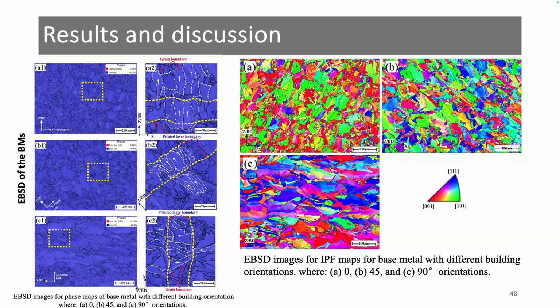Here we show the EBSD of the base metal. This one was at 0 degree, here 45, and here 90 degree. We can see that this dashed yellow line represents the printing layer boundary. And here we can find that the formation of the grain boundaries is parallel to the printing direction, or perpendicular to the printed layer.